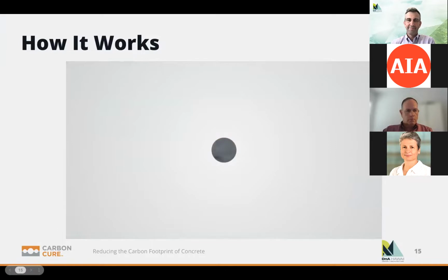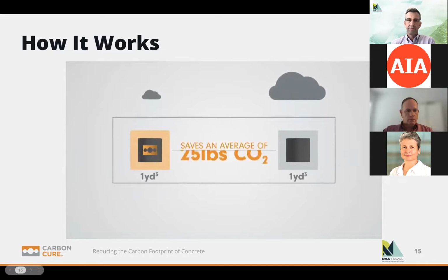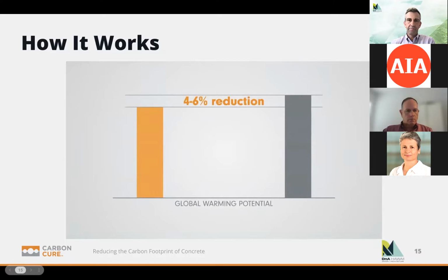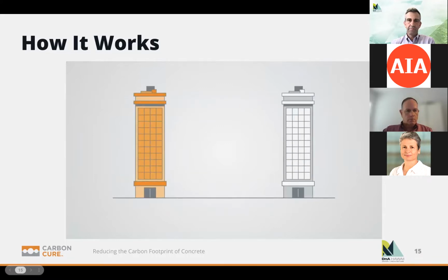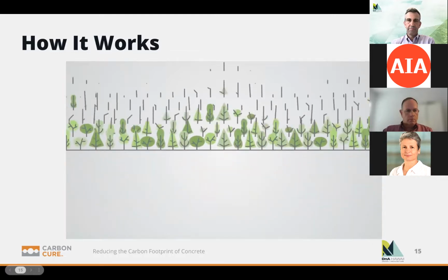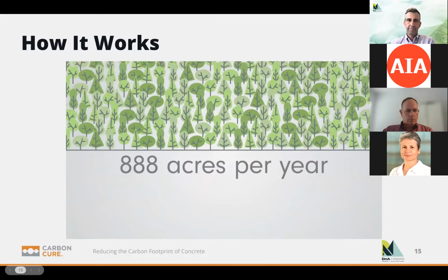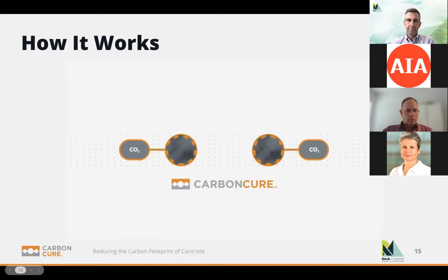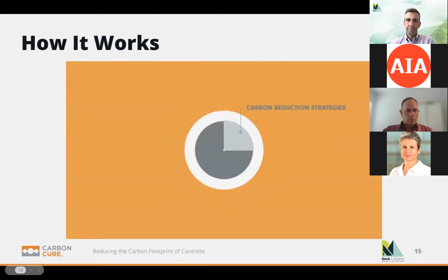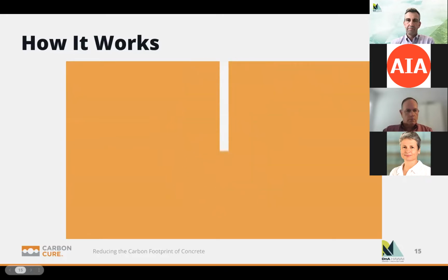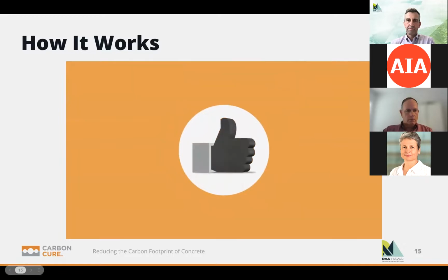Mineralized CO2 improves the concrete's compressive strength, which then enables the reduction of cement content in mix designs without impacting strength or performance. Every cubic yard of concrete produced with CarbonCure's technology saves an average of 25 pounds of CO2 emissions from entering the atmosphere and provides a 4 to 6% reduction to global warming potential. An average building built with CO2 mineralized concrete would save approximately 1.5 million pounds of embodied carbon, which is equivalent to the carbon absorbed by 888 acres of forest in a year. CarbonCure is compatible with all materials commonly used to replace cement in concrete, including fly ash and steel slag. This allows designers and engineers to stack CarbonCure among other carbon reduction strategies for maximum impact, supporting embodied carbon reduction goals and contributing to LEED points.